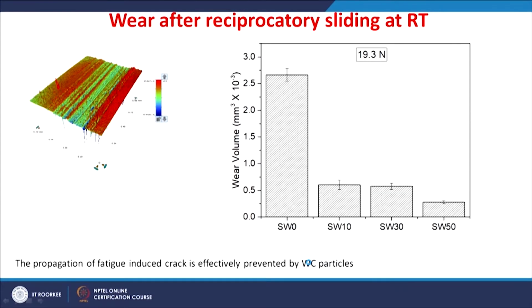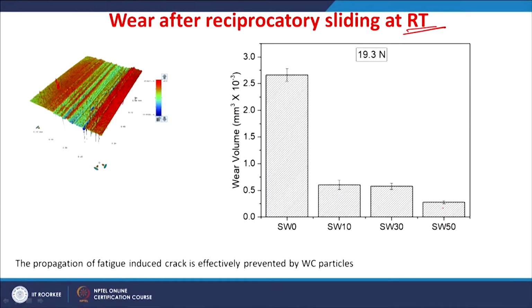Now, you see the wear volume of the composites worn at room temperature. As the tungsten carbide is introduced in the silicon carbide ceramics, the wear was substantially decreased. That means the reciprocatory sliding, which induces the fatigue-induced cracks, is effectively prevented by the tungsten carbide particles. This study was selected to understand the behavior of these composites in reciprocatory sliding.